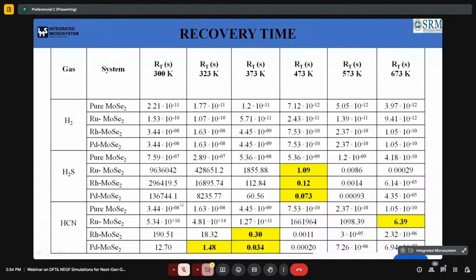From this gas adsorption analysis, we concluded that except for hydrogen gas, for all other gases, that is H2S as well as HCN, the system is showing good adsorption towards sensing. Based on the recovery time, we can conclude that the palladium doped system can act as a good sensor at room temperature for HCN gas adsorption, whereas the ruthenium and rhodium doped systems can act as a good sensor for H2S as well as HCN gas also, but not at room temperature, at a little bit higher temperature. So these are the main conclusions. Okay, thank you.